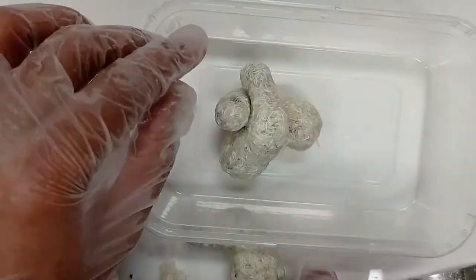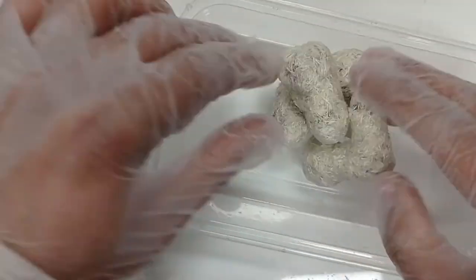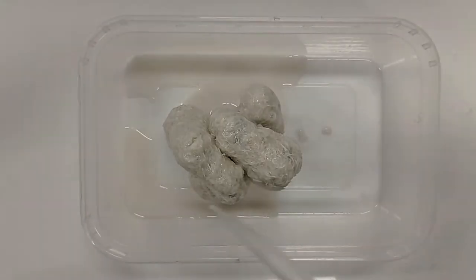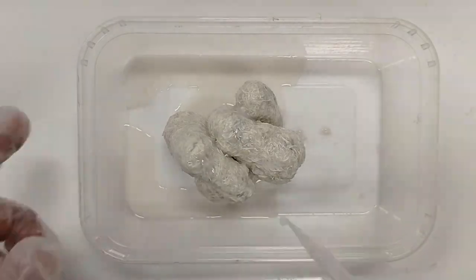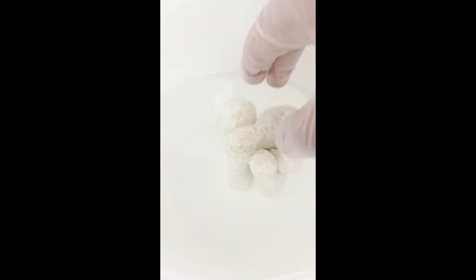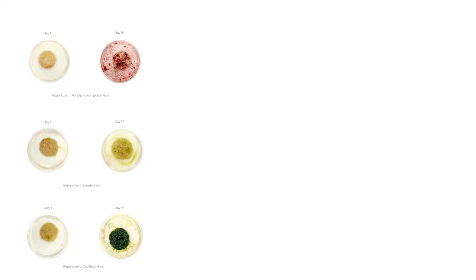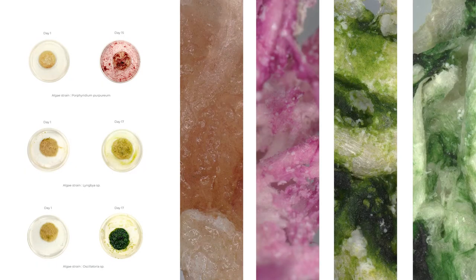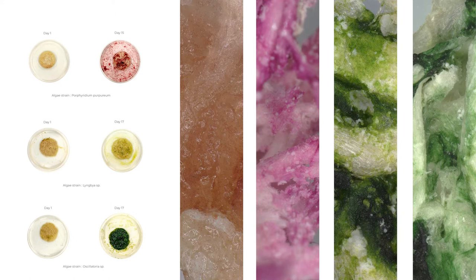The substrate is also used as a surface coating. Being a hydrogel composite, it has high water absorption capacity and current tests show that the substrate is immune to deterioration of saline water for more than a period of three months. Due to water absorption, it naturally favors algal growth as a substrate and proven receptive to a series of marine algae.